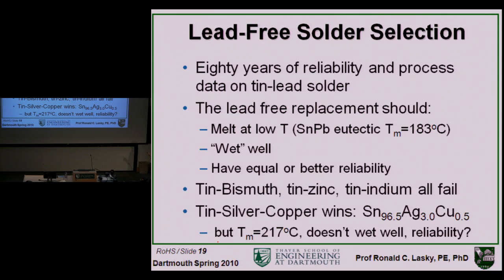96.5% tin, 3% silver, and 0.5% copper. But it melts at 217. That's 34 degrees higher than tin lead solder. And it doesn't wet quite as well.